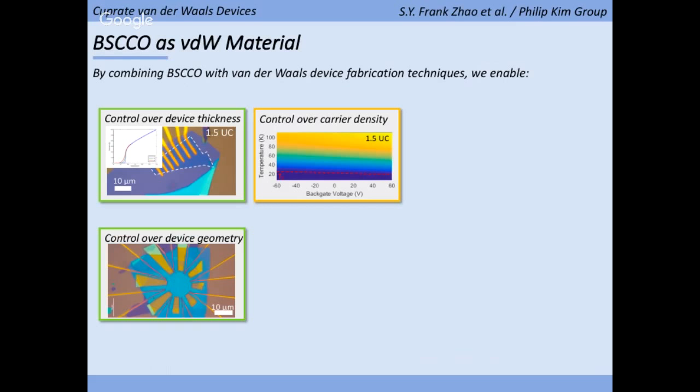And we actually see zero resistance, and we can tune this transition temperature a little bit by using nothing but a silicon backgate. Now, if we were to do a little bit better, and instead of using 1.5 unit cell, you go to, say, 0.5 unit cell, and you use a slightly better gate, such as a hexagonal boron nitride top gate, you can actually do a lot better. So that's something that we're working on. But to be honest,